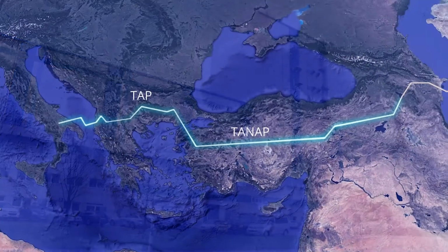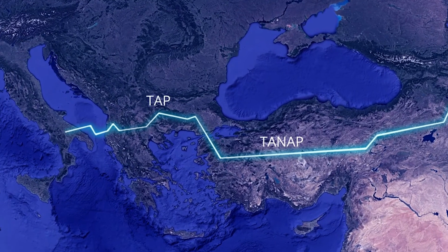For the Greek one, the TAP, we delivered 75,000 tons, again in X70, so the same grade, same concept from ArcelorMittal Bremen. The thickness was 17.9 mm, but with a more severe toughness requirement of drop weight tear test at -20 degrees on coil.